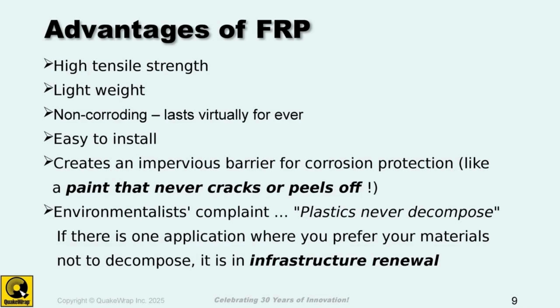And one benefit of this wet layup system, or in general really all of your FRP products, is that if you apply them to the entire surface, you create an impervious layer that keeps moisture and oxygen away from your structure. So it brings the corrosion process to a halt, because remember, for corrosion to take place, you need oxygen present. And if you stop that flow of oxygen, then you have actually shut off the fuel to the corrosion process.